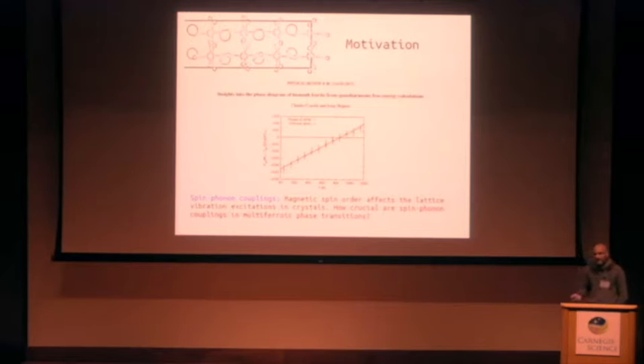At the same time, we just did quite a standard quasi-harmonic approximation in which we constrained the magnetic moment of the atoms to the one that you see in the ground state, right? To our surprise, we found out that in reality it didn't matter too much, at least for the rhombohedral polar to paraelectric phase transition at normal ambient pressure conditions. When you start heating it up, at a temperature around 900 kelvins, you get the paraelectric phase.